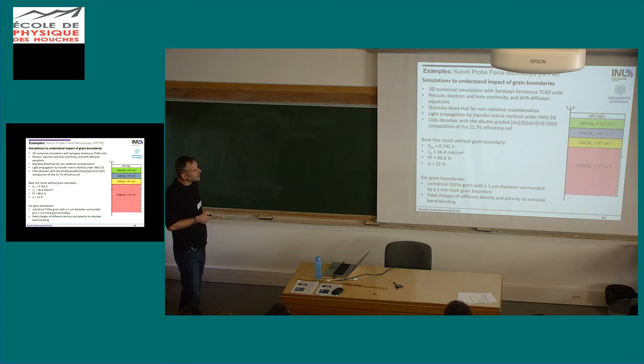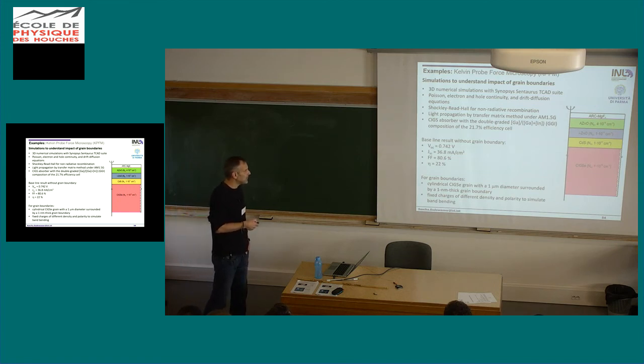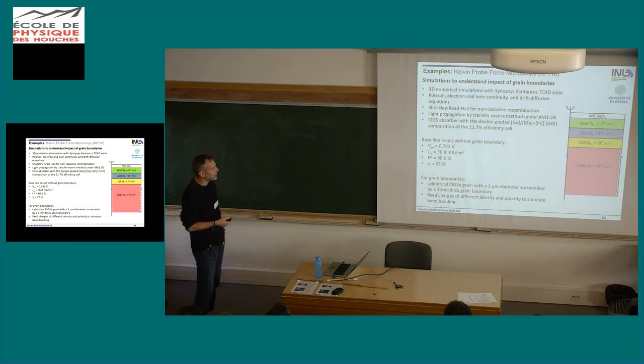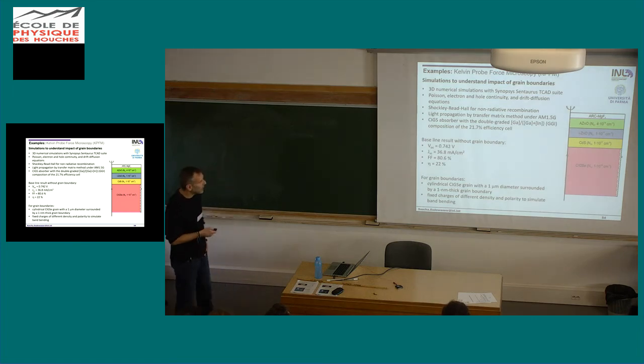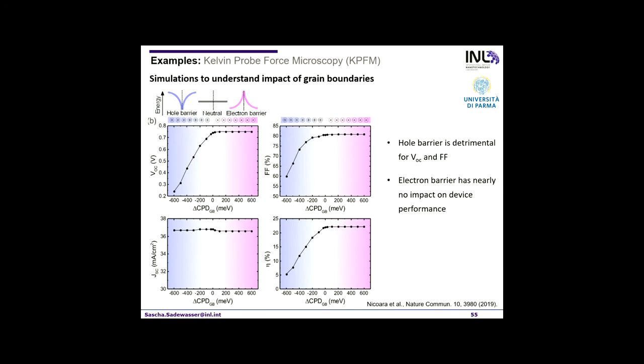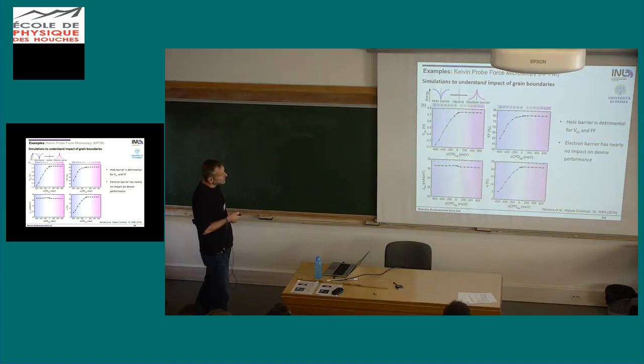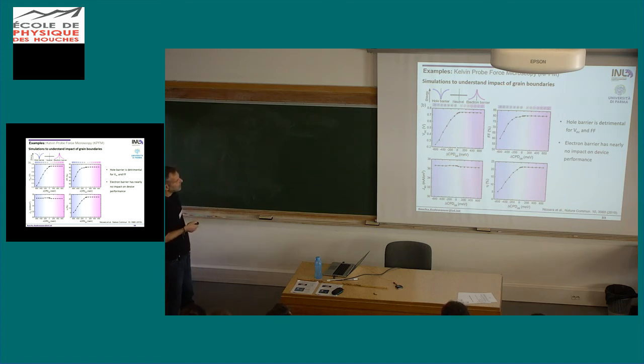And the nice thing in the project, they extracted by different measurements all the parameters for the real material that was grown in the study. So there's a baseline result. It's this one here. All these parameters are really taken from an experiment. And then a grain boundary with a 1 nanometer thickness was included, and fixed charges were placed at the grain boundary, and the polarity was changed. And then we looked at what happens for hole and electron barriers. And this is the potential change at the grain boundary for the different parameters. And you see immediately if there's an electron barrier, that doesn't affect the device properties at all. Only hole barriers will affect the device properties.